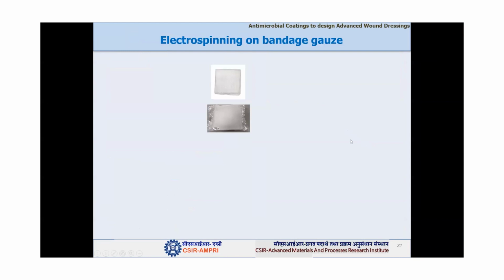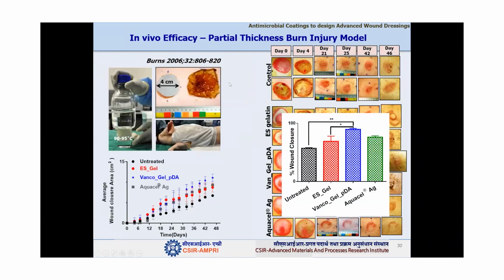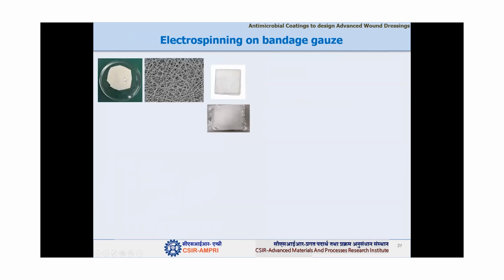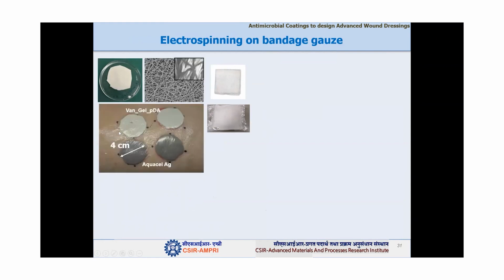Although the results were fantastic, one problem we faced is that these dressings are very tough. They are very tight dressings, so we need to soak them in water before putting them onto the wound. So in the next set of study, what we did was spin the fibers on a cotton gauze. So these are the dressings we received on the cotton gauze. This is the SEM morphology. And this is how we have put it on the pig. So now it is on the cotton gauze.